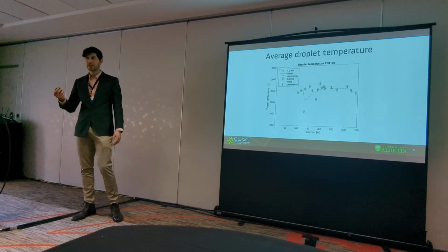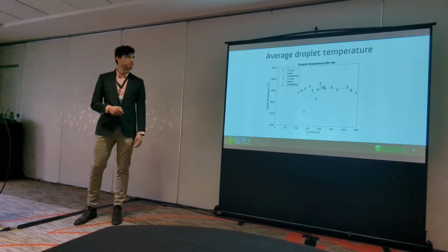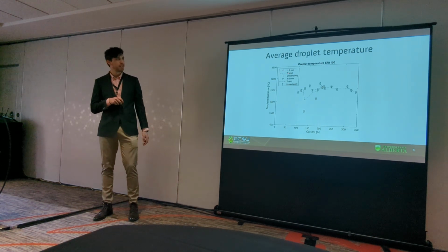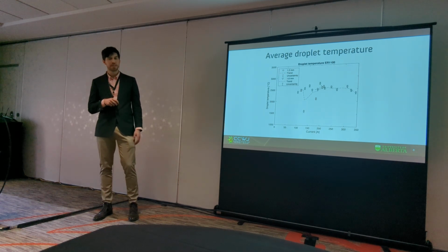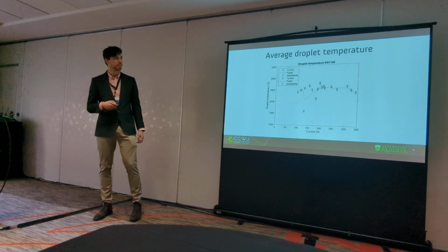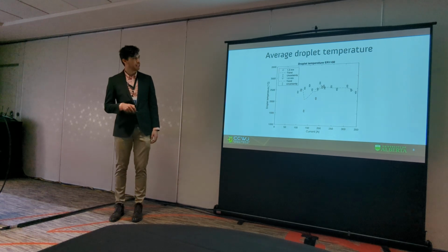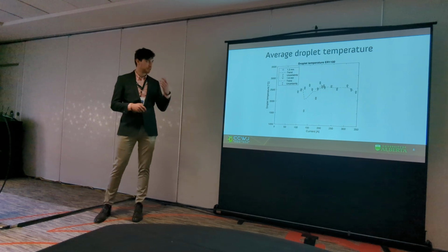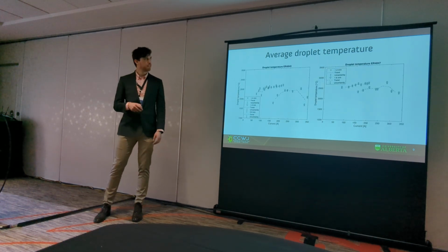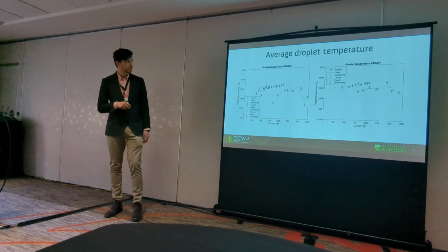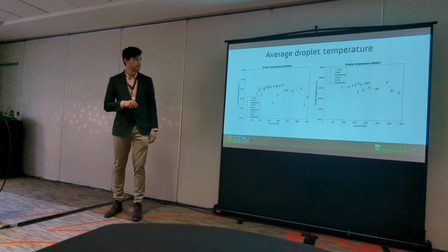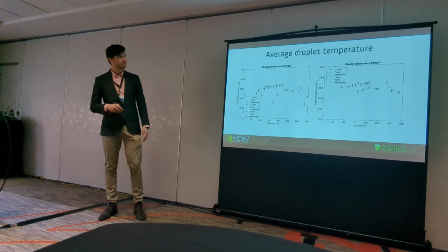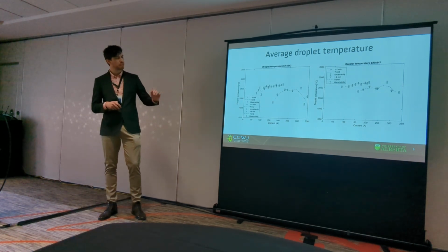So let's move on with the results. So for 1100, important thing, we did 2 or 3 diameters, 1.2 millimeters and 1.6 millimeters, and in some of them 0.9 millimeters to see how it changes. So we can see here 1100 is more or less constant at 2500 Celsius. For the next ones, 4043, we have 3 different diameters. We can see that they're more or less in the same range, the same as 4047. Those are more or less smooth, I would say.